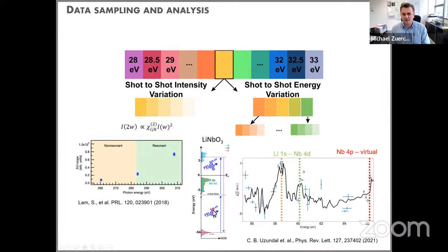And now we can see, compared to the first observations, there is very large richness in these spectra. And each of these humps and each of these features usually means a certain oscillator strength in a specific symmetry broken state. The other thing we found in this work, that we're actually near a niobium edge. So we also saw other resonances that pertain to niobium 4p states. So in this case, due to these very highly spectrally resolved measurements that we were able to do by establishing this new method, we were able to now get spectra with high spectral quality that allow us to even identify different elements of the system and their individual second harmonic response.